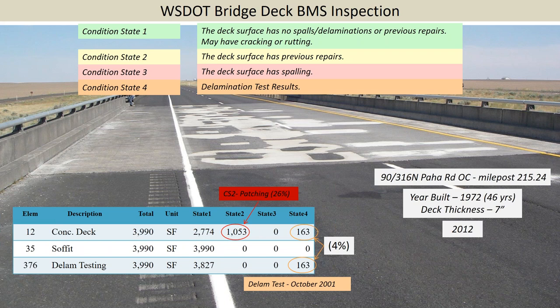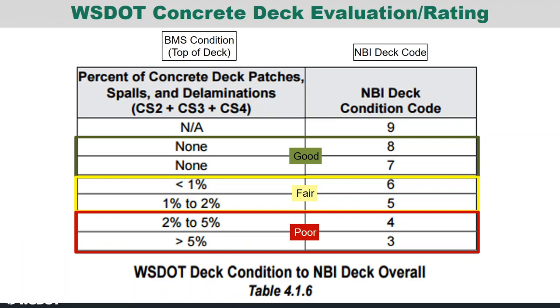On this particular bridge outside of Moses Lake, you can see that at one time it had over 1,000 square feet of patching, which added up to 26%. When we looked at this bridge, it was built in '72 with a 7-inch deck. It still seemed to be something we could rehabilitate, and so it didn't need to be fully replaced.